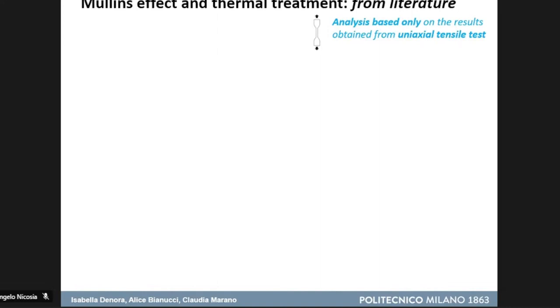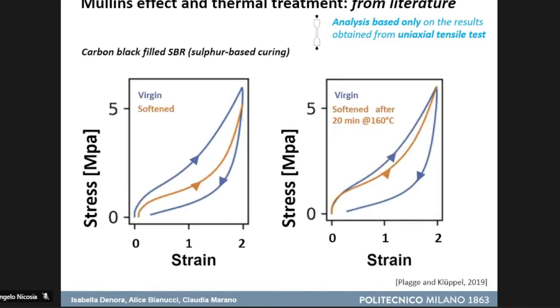For example, the reversibility of the Mullins effect. In fact, as already studied in literature, after a thermal treatment, the softened material can recover the mechanical behavior of the pristine material. Here there's an example in which we have reported the virgin and softened material mechanical behavior, and the mechanical behavior of a softened material after thermal treatment, in which we can see that the softened material has partially recovered its pristine behavior.